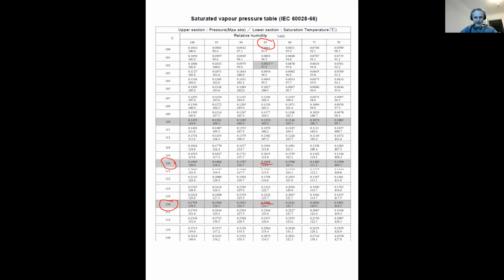And then the other number here states again the saturation temperature. So if we are running our test in 120 at 85% relative humidity, then we need at least 1.7 bars extra pressure. And if any of the surfaces are the temperature is below 115, then we get condensation. So at this temperature, then the relative humidity goes to 100%. So this is just the point. So in the standards, you have these kind of tools for analyzing the temperature humidity relationship and required pressure. Okay, let's jump back.